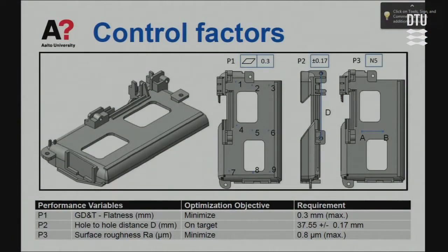So we just start tweaking parameters. Now I need to know what I need to measure to control. So we started with 3 simple geometrical tolerances. We took flatness, which was calculated at these points. It's a very important parameter in plastic devices and in mobile phones especially. So we took a dimension which has a requirement of plus minus 0.17, and the flatness has a requirement of 0.3. This needs to be minimized, this needs to be on target. And then the surface quality, that's kind of a weak parameter. Everybody knows that the surface quality of a 3D printed part is bad. That needs to be minimized, with a requirement that it be lower than or equal to 0.8.